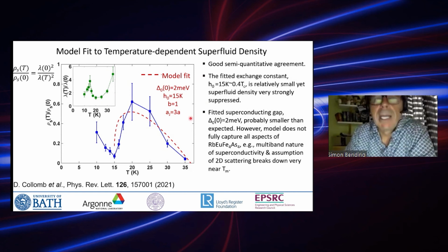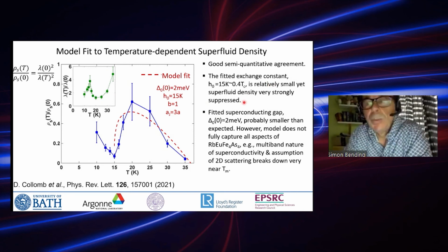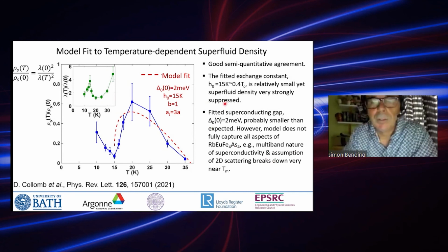There are many questions you might ask about the fit parameters. So the fitted exchange constant of 15 Kelvin, that's about 0.4 of Tc, which is relatively small, yet we're seeing, nevertheless, very strongly suppressed superfluid density in this case. The value of the gap of 2 millielectron volts is probably smaller than one would expect. However, I do emphasize that the model does not capture all of the aspects of this very complicated material, which is a multi-band material. It has different gaps on different bands, and also the assumption that we're dealing with 2D scattering is an assumption the model will break down very near Tm, where the spin correlation length diverges. But nevertheless, I think the agreement is certainly very satisfactory.